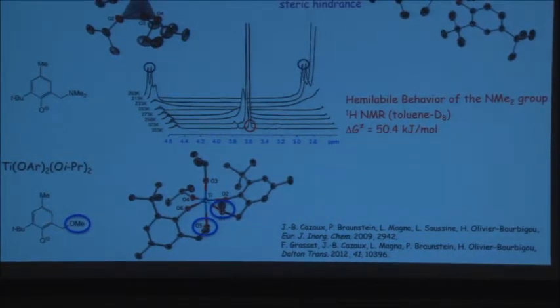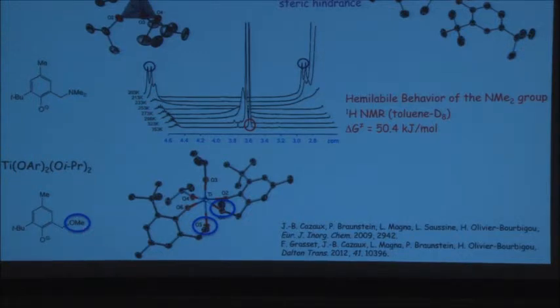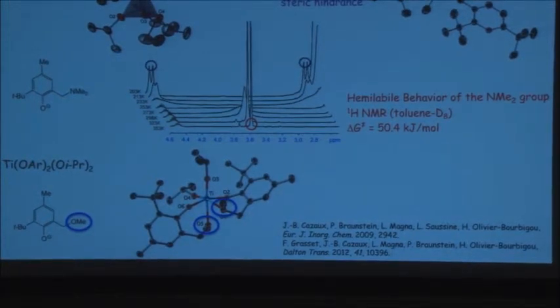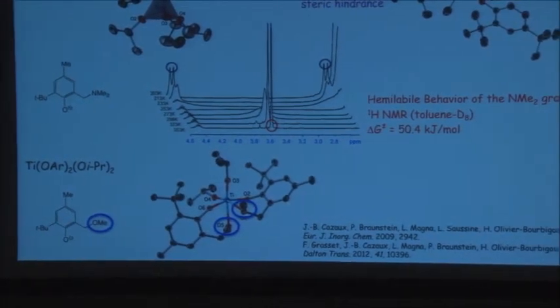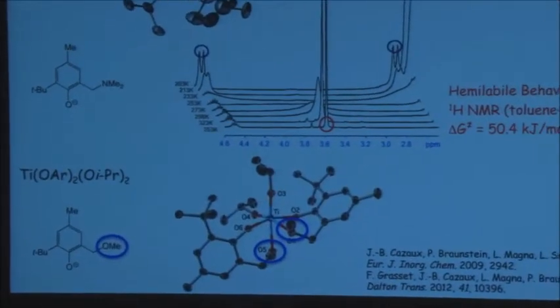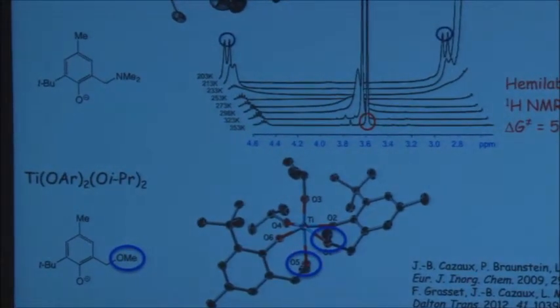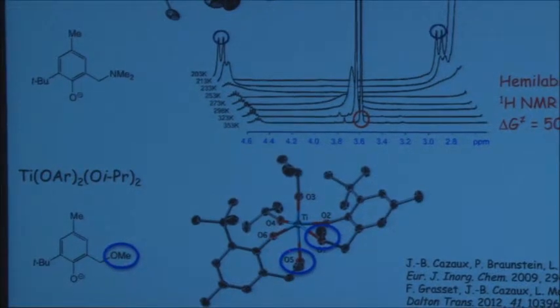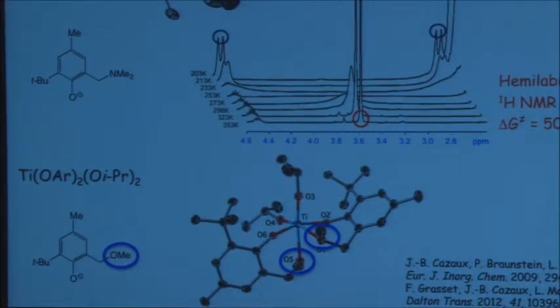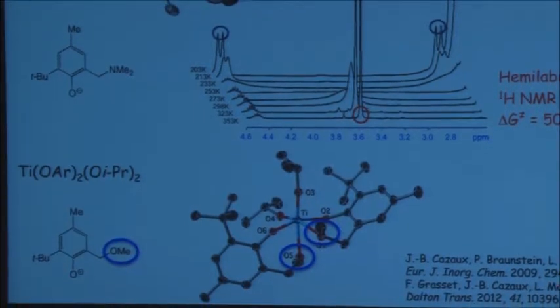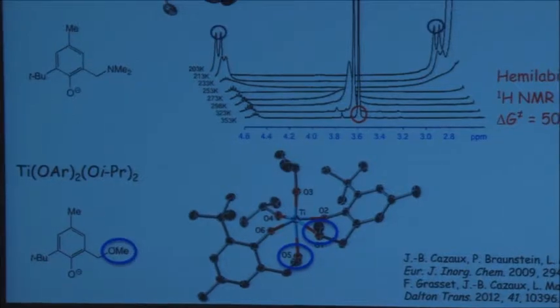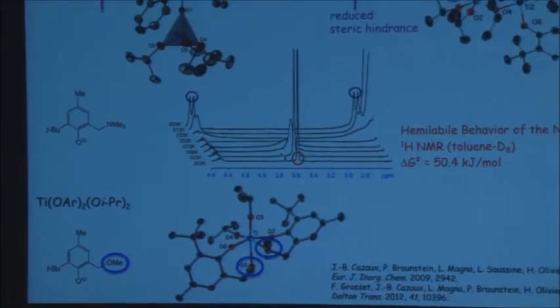However, if we now move to the methoxy analog here, we could characterize the compound by X-ray diffraction, and now we see a mononuclear titanium center, which is octahedrally coordinated, and the 2 methoxy groups are actually coordinated to the metal center. So in a way, it makes sense, because titanium-4 is much more oxophilic than nitrophilic, if I may say so.